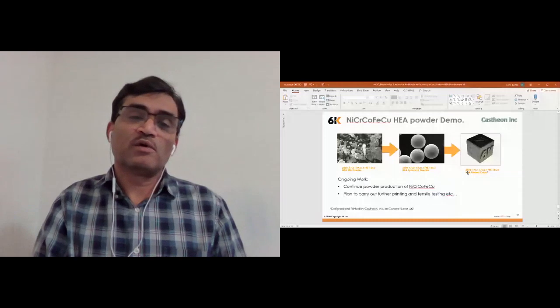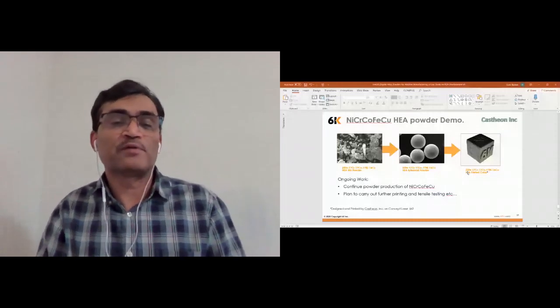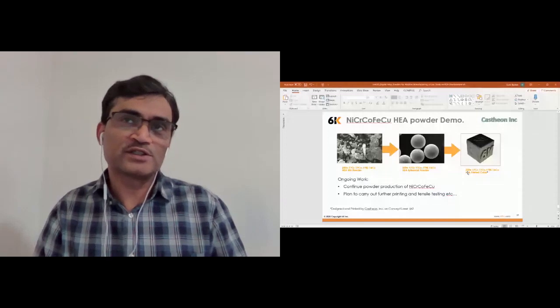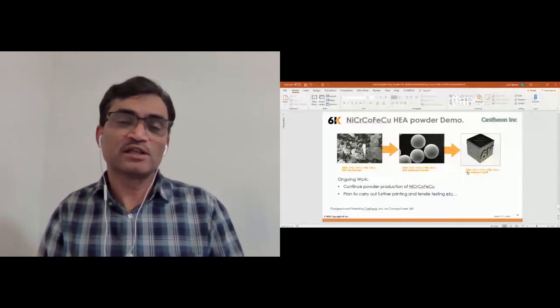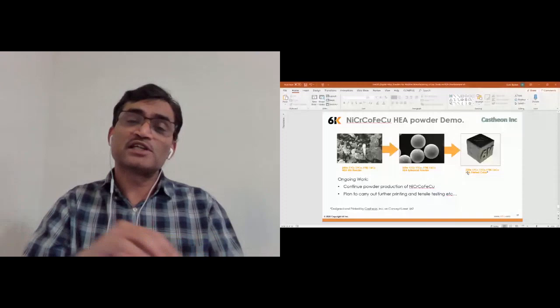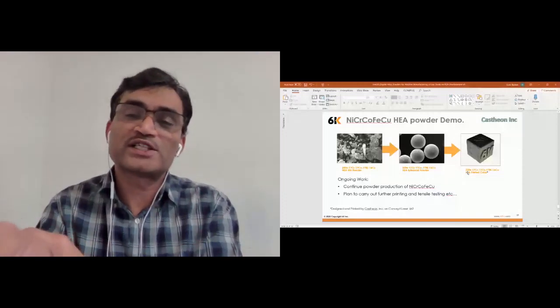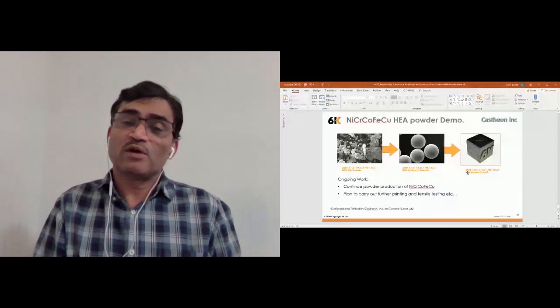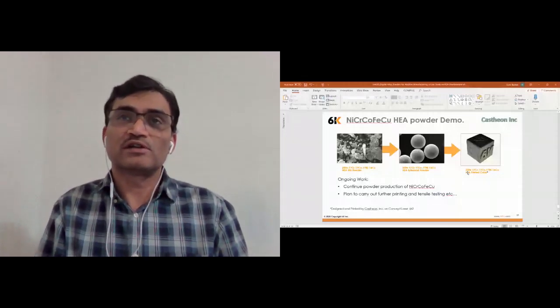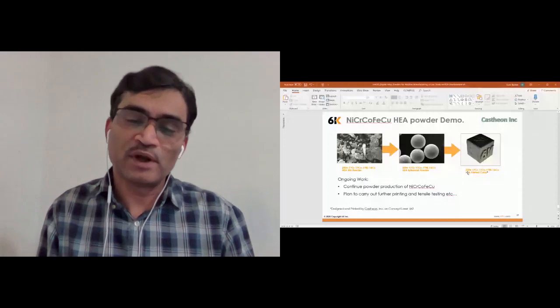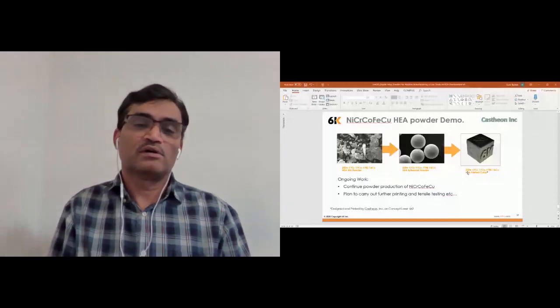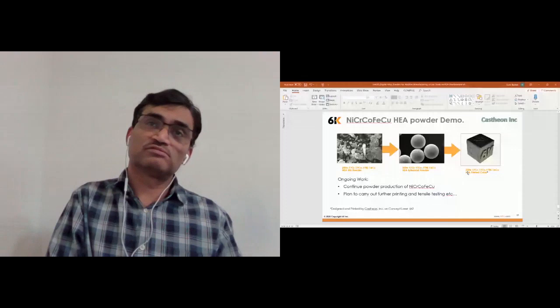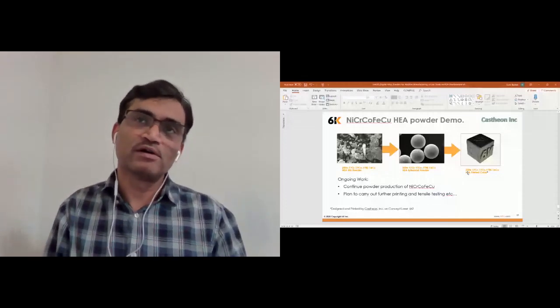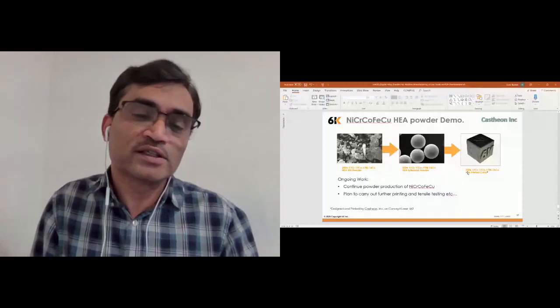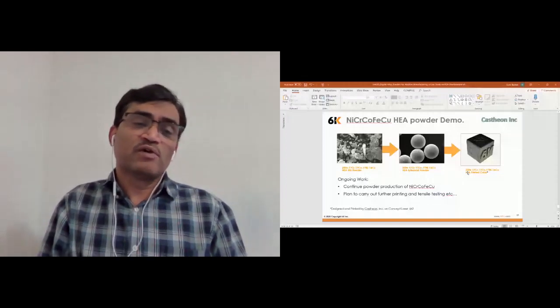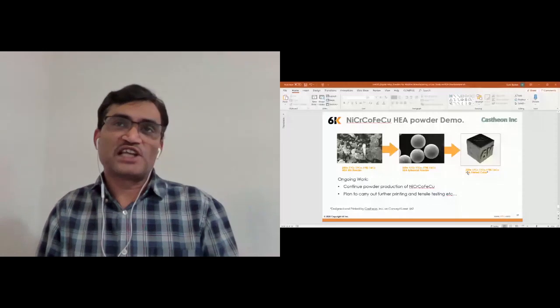So we are still working on this high entropy alloy process, where we want to print the actual test bars and test them for mechanical testing. But as far as the printing of this tube, which Castheon designed and printed, as far as we know, this is the first additive manufactured high entropy alloy tube or solid, because we have not seen any spherical powder for high entropy alloy yet. So the continuing work is printing the test bars and testing them.